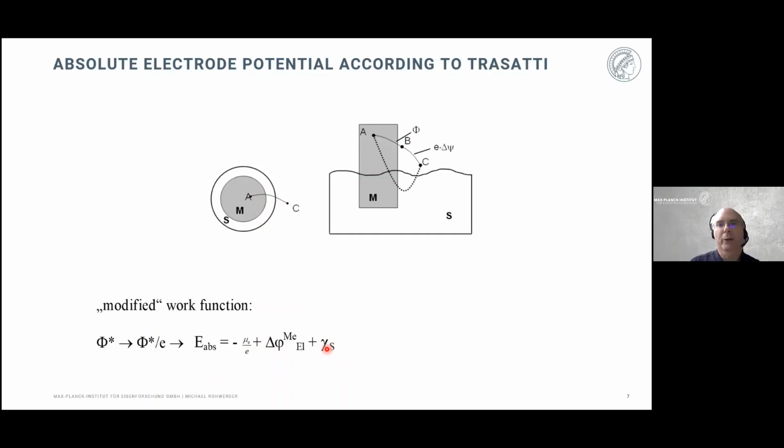Now, if you look at the third picture here, you see that it looks more like an electrode, right? Immersed in electrolyte. And now you see what we just considered is this pathway, right? But from the energetics, it is equivalent to go outside the metal. That's the work function of this metal. And then, because metal and electrolyte are charged in respect to each other, there is an electric field outside.